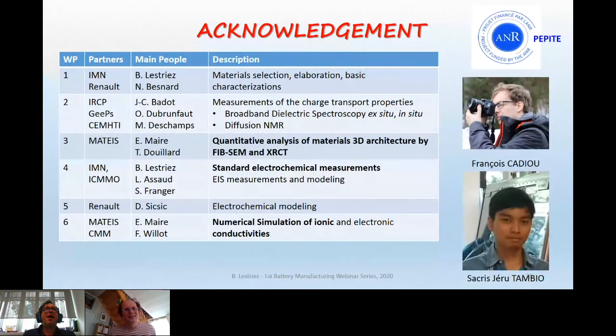I understand. I missed your first part. Maybe you already mentioned it in the first part of your presentation, but how could you conclude whether the CB is below the percolation threshold? Okay, I haven't shown this here, but simply by looking at the geometrical connectivity of the CB-PVDF domains, it was 100% certain that they are distributed and not connected to each other. And also when we did electrical measurements, it was very clear that for the electrodes containing the higher amount of CB-PVDF, the activation energy was metal-like conductivity, that is to say, typical of CB-PVDF above the percolation threshold, while for the electrodes below the percolation threshold with a low amount of CB-PVDF, the activation energy was a mix of the activation energy of CB and NMC.